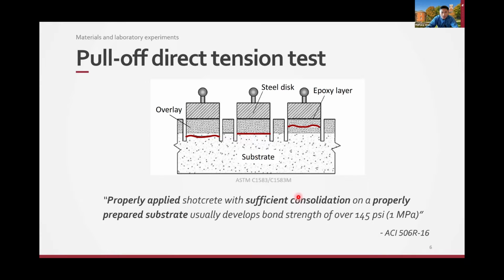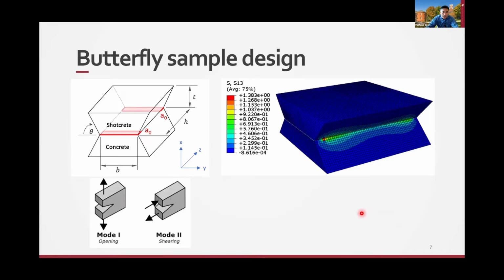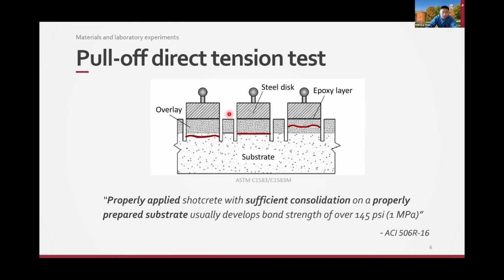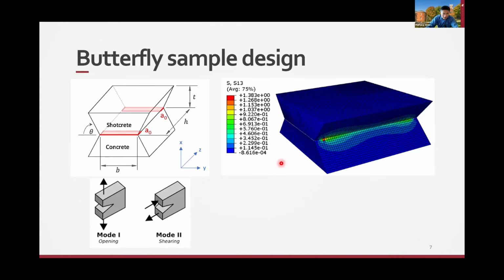ASTM has some number that typically for the pull-off test, we call this one the pull-off test. Typically, the bond strength needs to be 1 megapascal or 145 psi. Also, the test method we're talking about here is typically used in the field and is not that easy to do in the laboratory. So that's why we try to come up with a new test method for the laboratory.